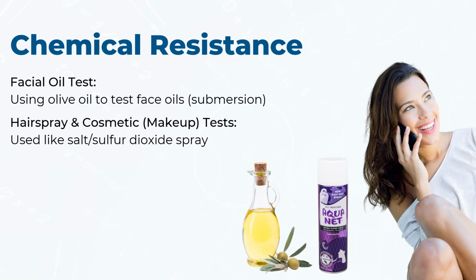Here's another kind of off-the-wall test. With smartphones, we have our lovely lady here exhibiting using a smartphone. People have different facial oils and makeup. The oils from your face, if they get on a coated surface, can definitely start to eat a film. So how can we simulate the oils in someone's skin? What was decided on was essentially an olive oil and water mixture. You submerge the coated optic, remove it after a set period of time, say 10 minutes, and look for any coating removal. Again, you're looking for any adhesion loss, any hazing, any crazing, any induced stress.